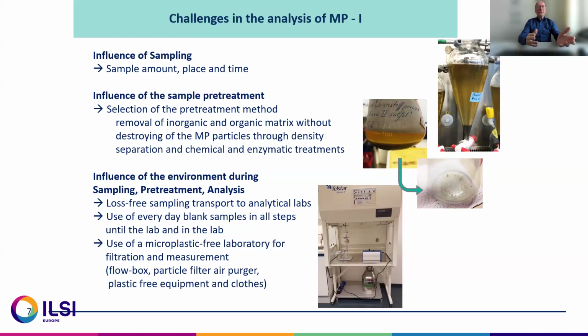And you should use, especially if you go to microplastics and nanoplastics below 10 microns, a microplastic-free laboratory for filtration, measurement, and so on. The best way is to have a clean room. A clean room is necessary if you go below 2 microns.